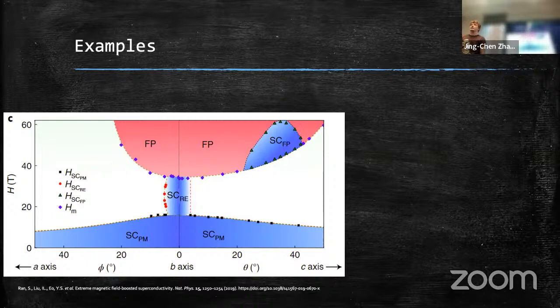It's the angle of the magnet with respect to the sample. Yeah, exactly. Normally, I think of tetragonal systems, I could draw it, but it won't be on the camera. Say you have a square-shaped sample with a little bit of thickness to it. For normal tetragonal systems, you have your A and your A, so anywhere in plane is fine. Then your C axis points outside. So if you apply field along C, that's what you normally do. But you can also rotate your sample so that you're applying the field along A, and you might get different properties. In this material, there's a different symmetry, so A and B are not identical.